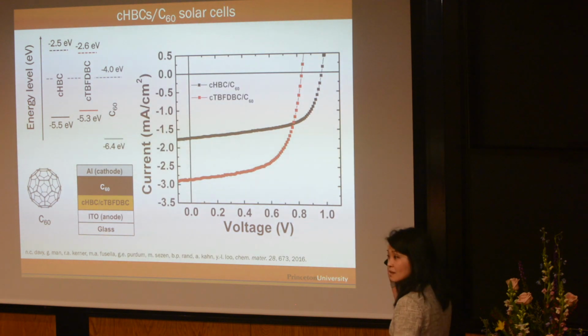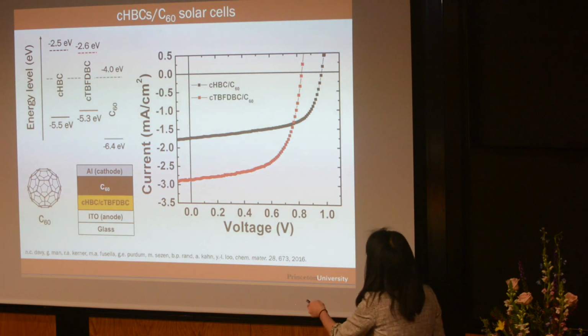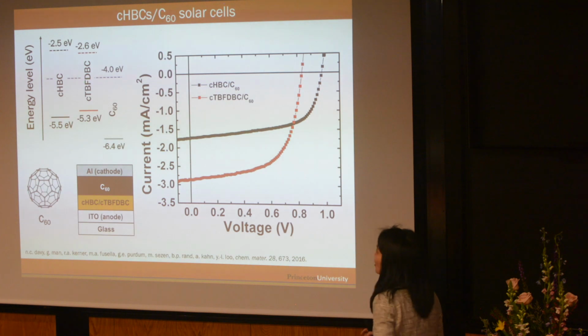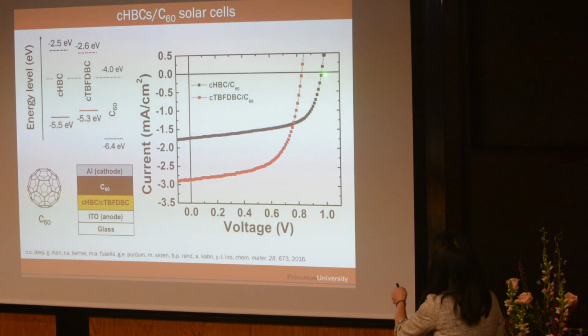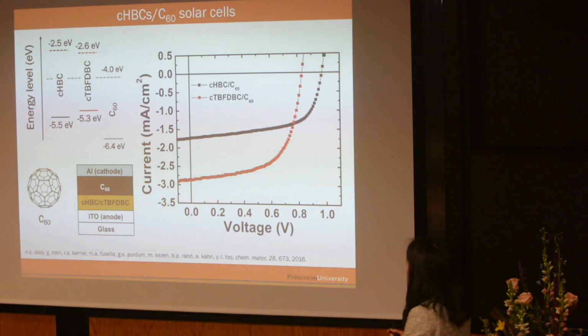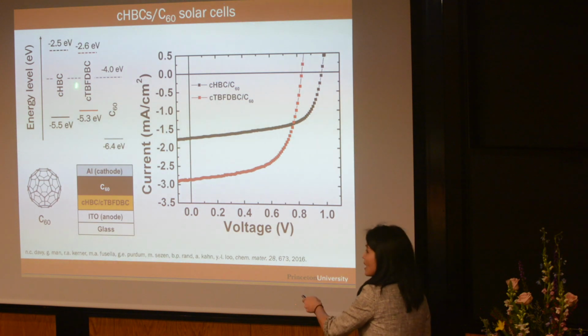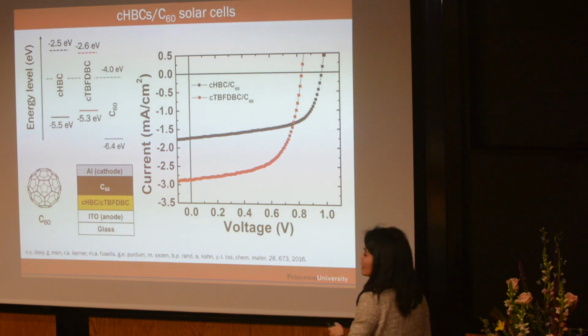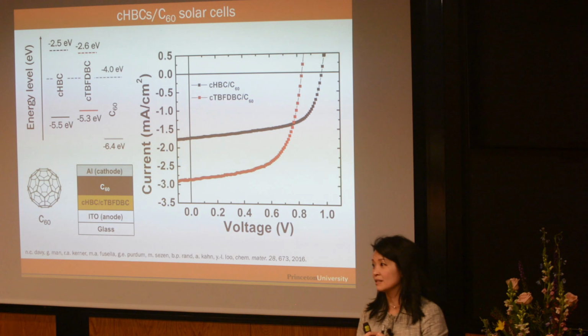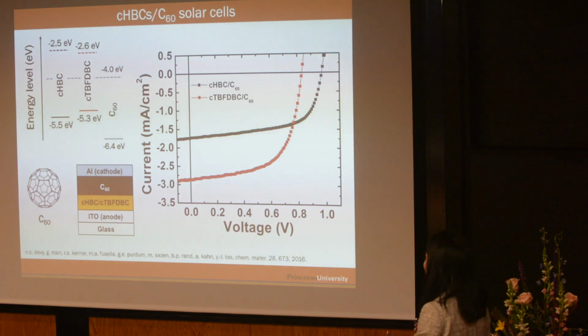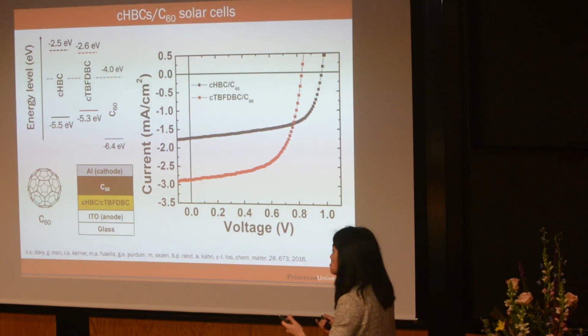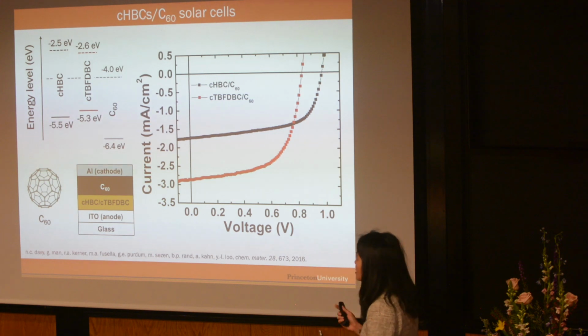Now, to first order, this makes sense, right? Because you can see that the HOMO of CHBC is lower than the HOMO of TBF, and so we get a higher open circuit voltage. And because this has a smaller band gap, we're absorbing more light, and so you get a higher short circuit current density. The cells behave nicely. We just have very low current. Suffice to say that the compounds behave nicely.